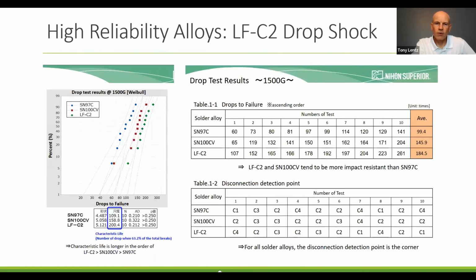Here's the data for drops to failure. SAC305, which is also called SN97C, had 99 drops to failure in this test. SN100CV had about 50% higher life there, 145 drops to failure. And then LFC2 almost doubled the performance of the SAC305 with 184 drops to failure. So they're definitely more impact resistant than SAC305.